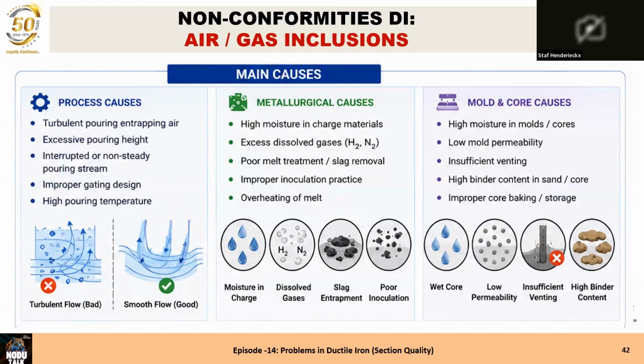Mold and core causes: high moisture in the mold or the cores, think of your monsoon season. Low mold permeability for green sand, because chemically bonded sand has no mold permeability, so it's mainly for green sand. Insufficient venting is very important, the venting should be on the highest point, but also at the end where the metal stream is flowing when the casting is filled.